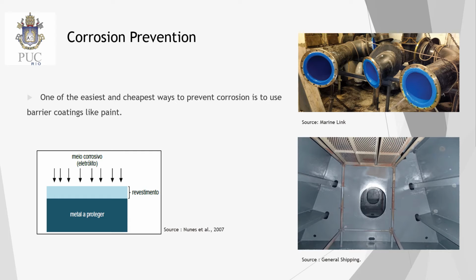In the present work, the novelty compared with previous work is that the organic coating studied was an ink, which is basically composed of a Novolac Type 2 industrial epoxy resin, however, without the addition of pigments and fillers. Here we have a figure showing the coating, that is your polymeric material, the resin, between the electrolyte and the metal that we are going to protect.